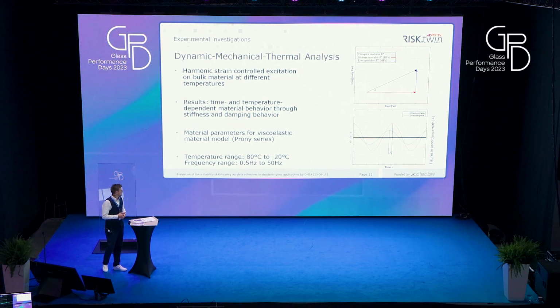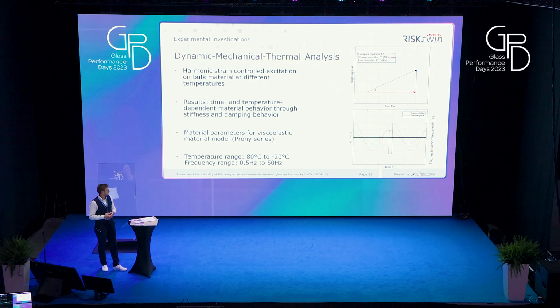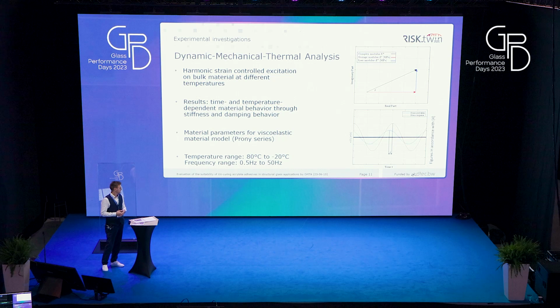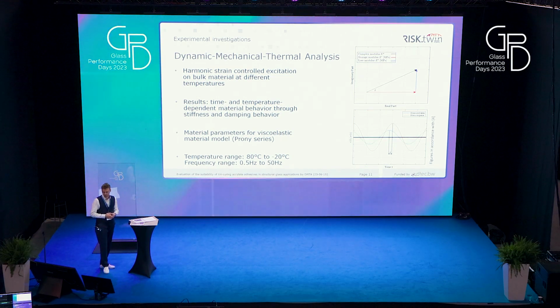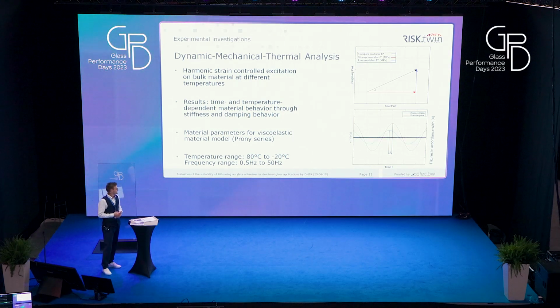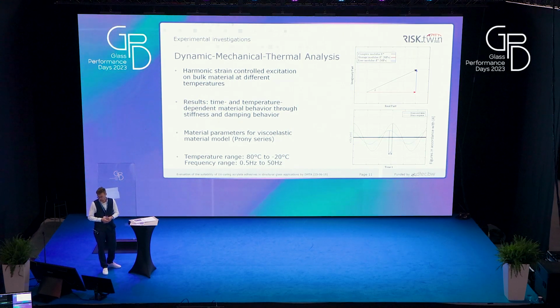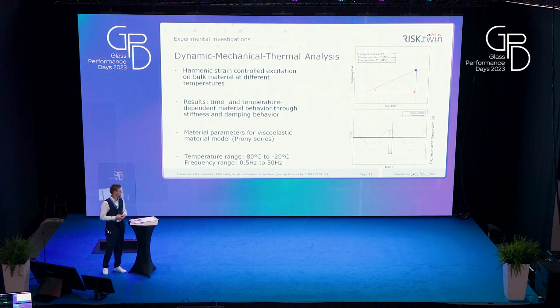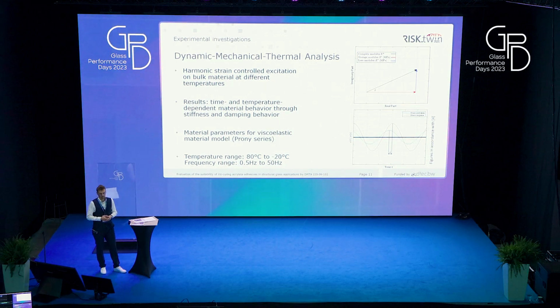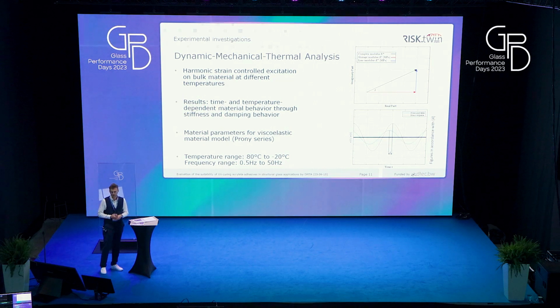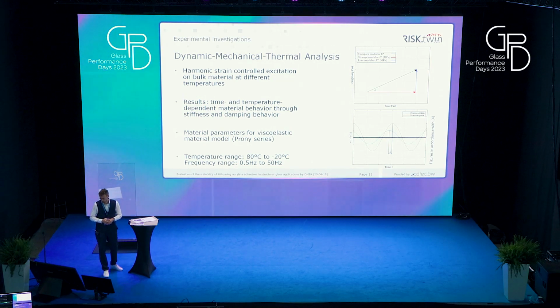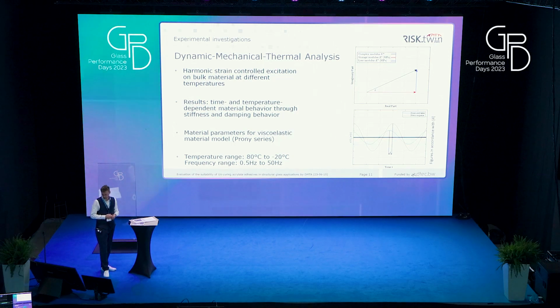So to illustrate this, we can see in the bottom picture on the right-hand side the strain excitation plotted in blue. And for a viscoelastic material, as we have here, there is a phase lag between the excitation and the stress response of the material, which we call the phase angle delta. And with this phase angle delta, we can span a triangle in the complex plane in the upper picture with the so-called storage modulus and loss modulus, where the storage modulus represents the elastic part of the material behavior and the loss modulus represents the material damping behavior. And together they are combined in the complex modulus.